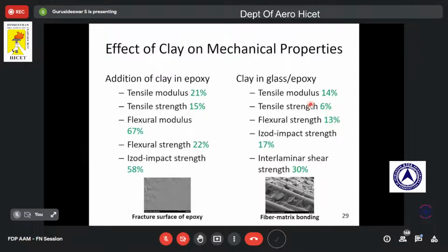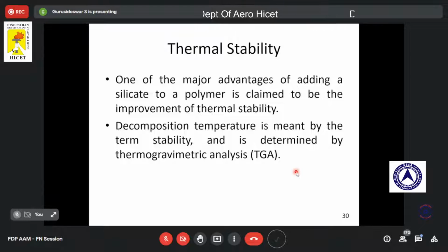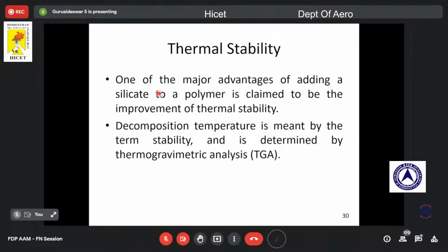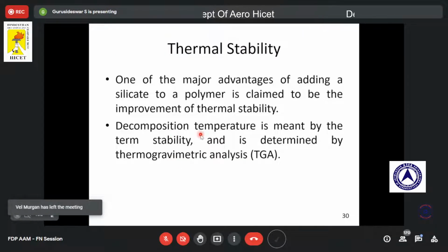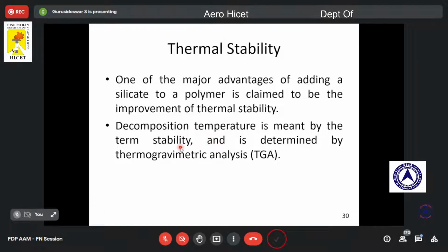We also did thermal stability. We wanted to understand the effect of clay on thermal stability. Again, we have found that the addition of clay in epoxy leads to better thermal stability. So we have got a shift in the decomposition temperature. With the addition of clay in epoxy, the decomposition temperature has been shifted to a higher level. This is what we observed from the thermal stability. This test was done on a thermogravimetric analyzer. From this we observed that addition of clay leads to better thermal stability.